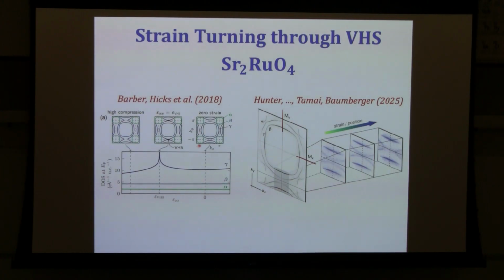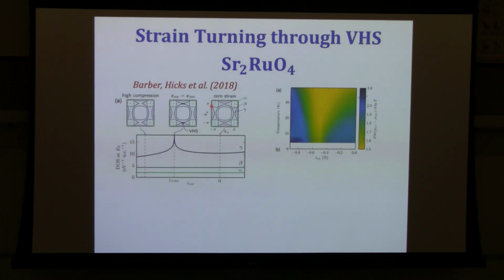And what Cliff did back in 2018 is to measure the electrical resistivity as a function of temperature and strain, showing this kind of phase diagram. So this axis is compressive strain, and this axis is temperature. What's plotted is the log derivative of the resistivity, where you subtract the zero temperature extrapolation of the resistivity. So this gives you, if you like, the local exponent with which the resistivity is varying as a function of temperature.